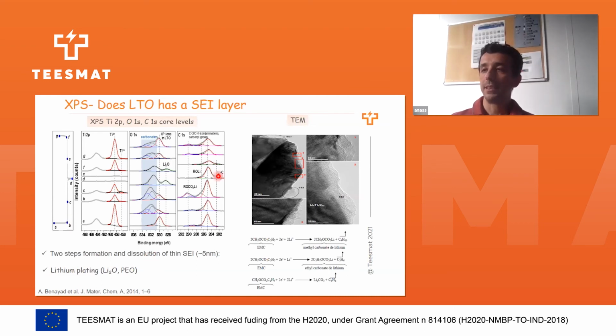And from this claim here, we can imagine some chemical reaction that explains the process of formation for lithium carbonate. For example, the decomposition of EMC, ethyl methyl carbonate, through a bielectronic process to form methyl carbonate with some degassing, or through a monoelectronic process to form lithium carbonate. So that could be one of the reactions that could be at the origin of this peak that we observe in the carbon.